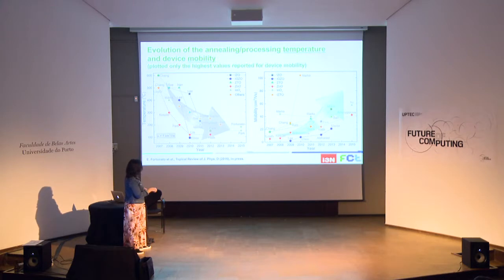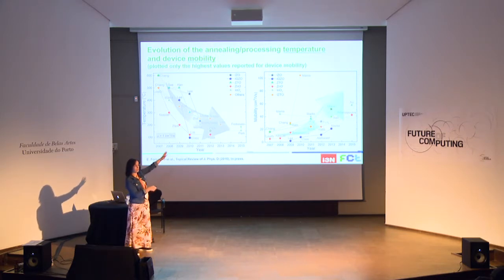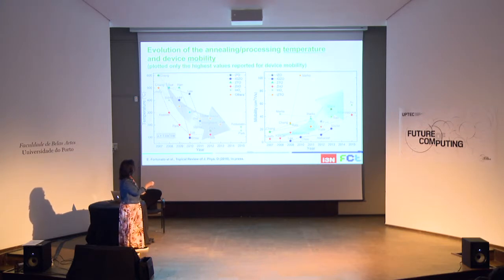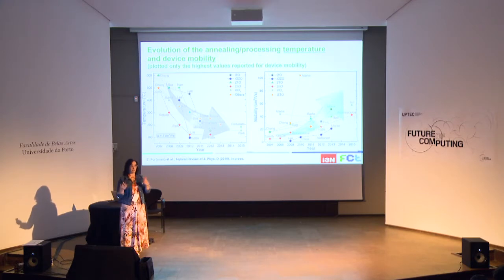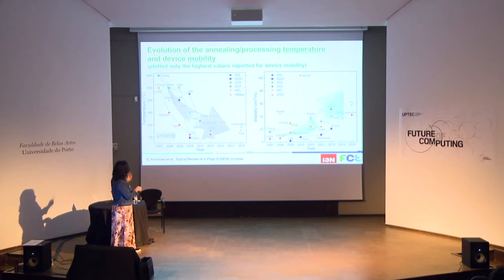And what we observed in the last years, for example, here I plot some TFTs based on these materials, and these materials are the semiconductors, like silicon, indium zinc oxide, indium gallium zinc oxide, zinc tin oxide, and so on. Here I plot the temperature and the mobility. Since this technology is based on chemistry, in order to promote all the reactions among these different reagents, I need to add energy. And usually the type of energy is heating. This is why temperature is important.